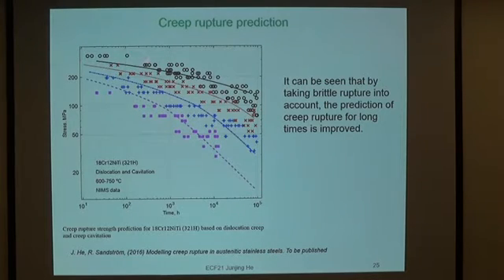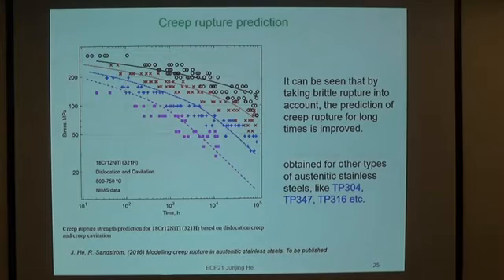And here are the final results for the creep rupture. This is the rupture prediction based on the combination of the two models. So by taking the brittle rupture into account, the prediction of creep rupture for long times is improved. So one can see there are two regions in the figures. And also similar results have been obtained for other types of austenitic stainless steels like types 304, 347, and 316.